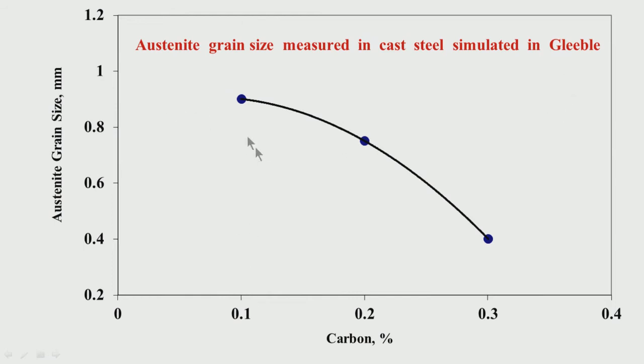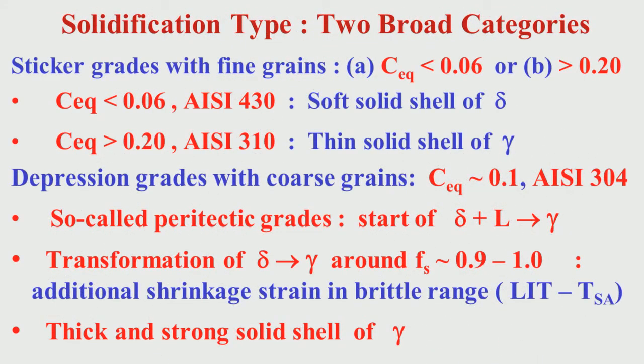So, around 0.1% carbon it is quite large, while at 0.3% carbon it is relatively less, say around 0.4 millimeter. And here it is about 0.9 millimeter, quite a large size. So we have tried to explain that, depending on the type of solidification, there are two broad categories. One is sticker grades, which have a sticking tendency during solidification, and the grains will be finer, as I have explained.